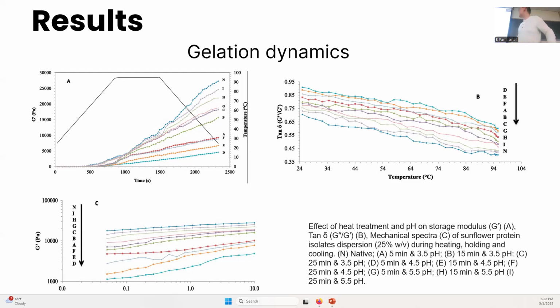Treated protein. The right corner shows the definition of different letters. N means native, and the others are treated under different treatments. The treated protein isolates had lower G prime values than gels prepared from native protein isolates. The protein isolates near isoelectric points had a lower tendency to form gel, and the lowest gel strength was obtained at pH 4.5, which is the blue line at the bottom.